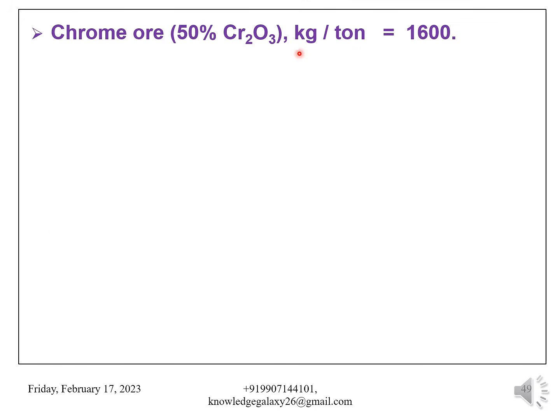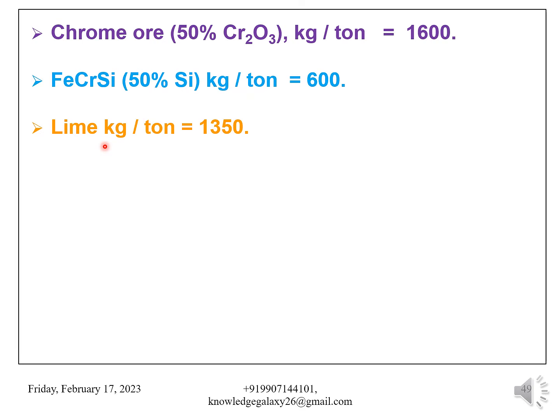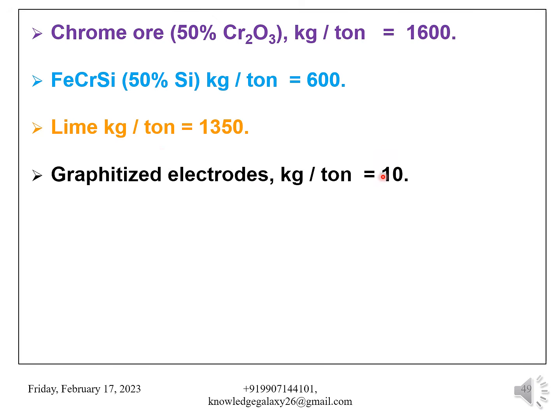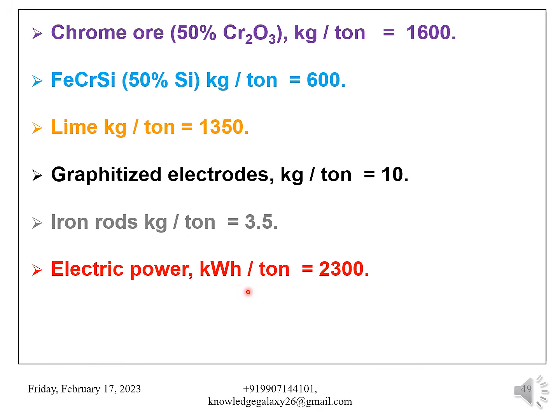Chrome ore, 50% Cr2O3, its consumption is 1600 kg per ton. Next is ferrochrome silicon, that is the reducer, 50% silicon, its consumption is 600 kg per ton. Lime, 1350 kg per ton. Graphitized electrodes, 10 kg per ton. Iron rods, 3.5 kg per ton. Electric power, 2300 kWh per ton. And chromium recovery comes to 82%.